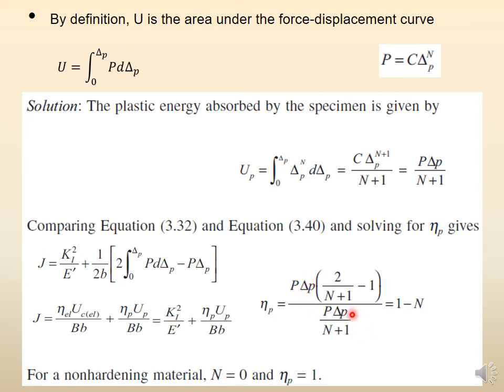The simplification is straightforward arithmetic, not something very complicated. So eta_P equals 1-N. This is the whole solution for that double edge notched tension DENT sample. If you start with this definition of U and this given equation in the problem, then you get this, and comparing this to this, you get this and simplify it, and it comes out to be 1-N.